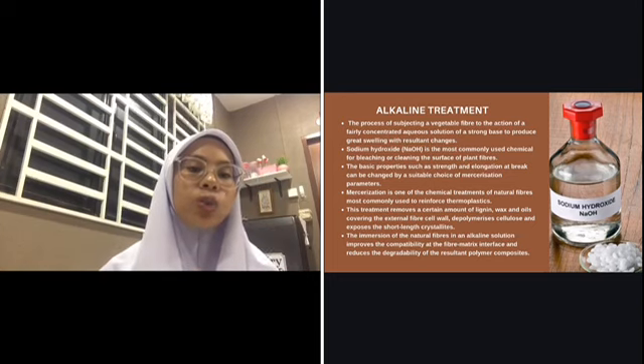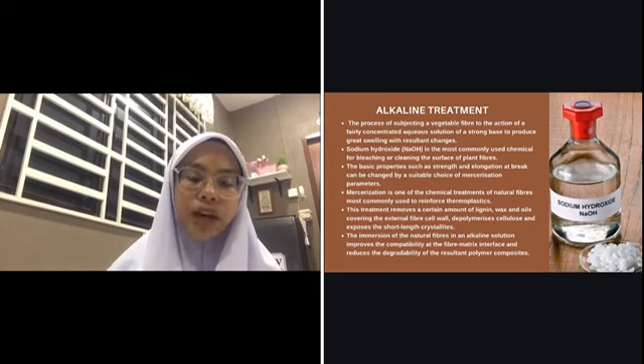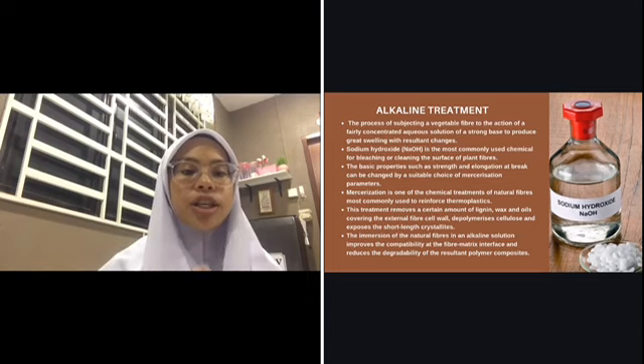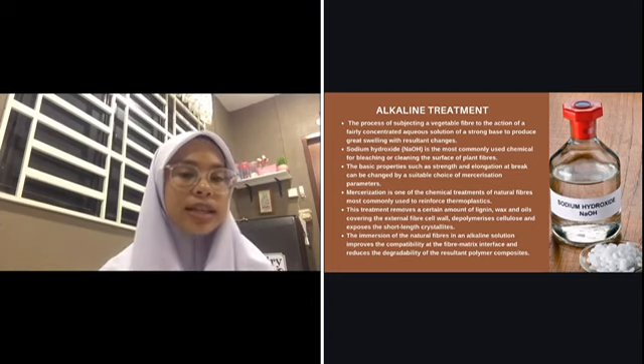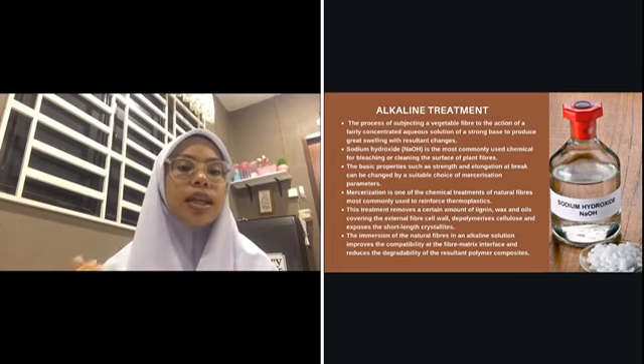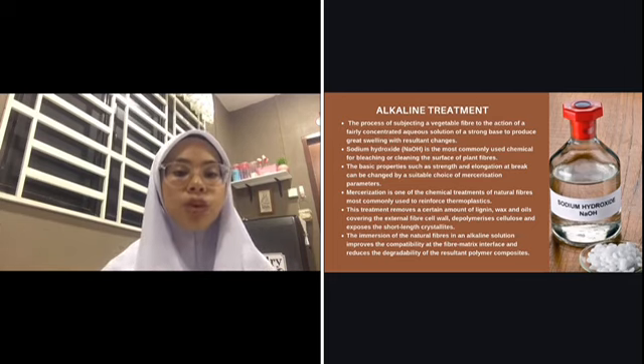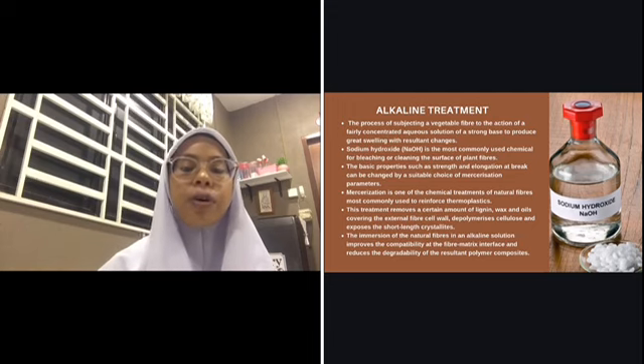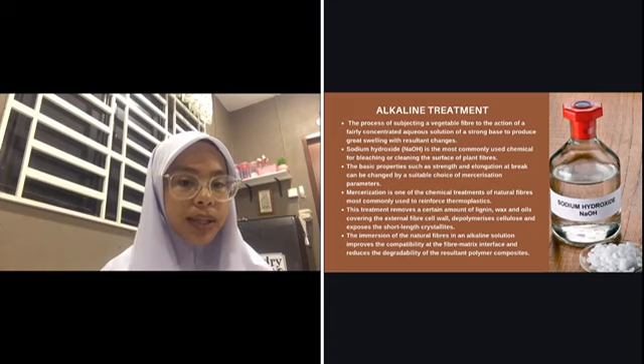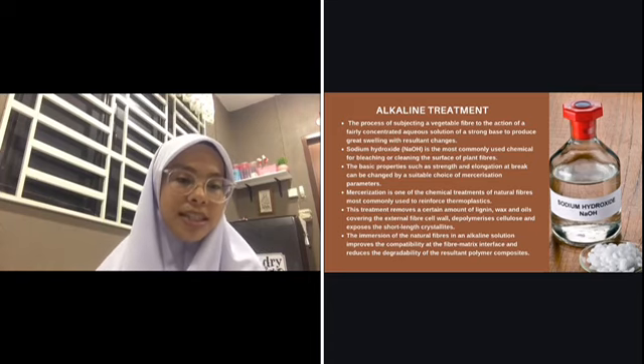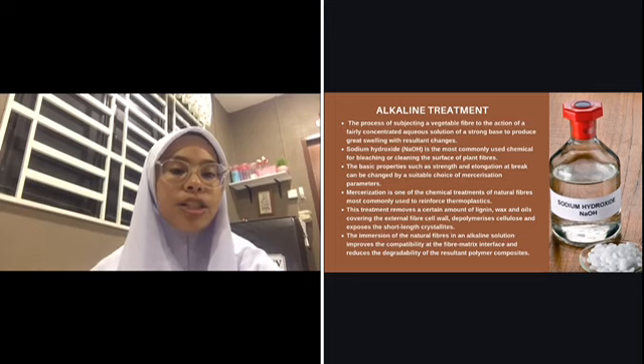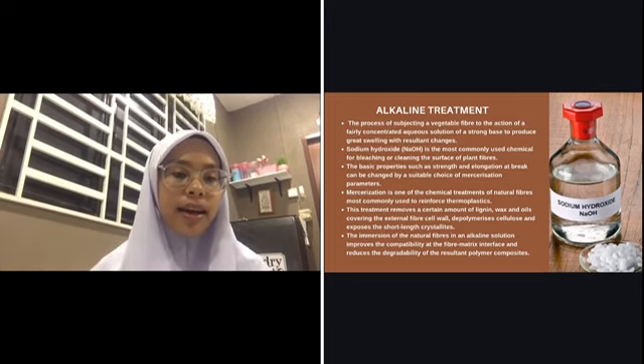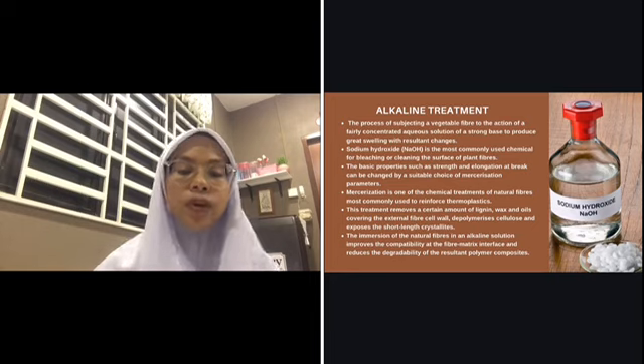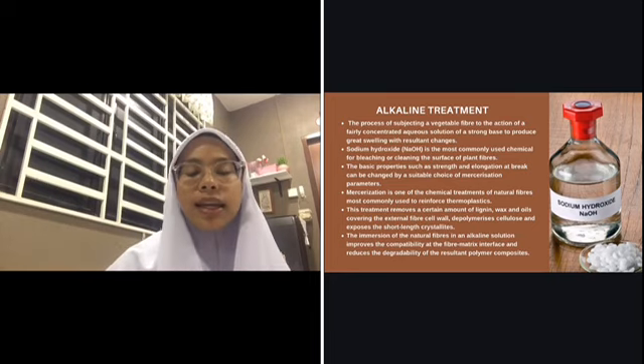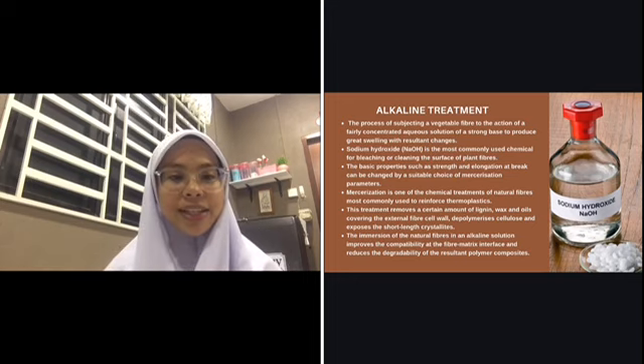So therefore, in order to improve the compatibility between the natural fiber and the polymer matrix, the natural fiber is immersed in an alkaline solution such as sodium hydroxide for a specific time duration at a specific temperature. It has been noted that the immersion of the natural fibers in an alkaline solution improves the compatibility at the fiber matrix interface and reduces the degradability of the resultant polymer composites. So to sum up, a lot of research has been done in the last decade, and it is proven that FRPC with the usage of treated EFB and polypropylene as the matrix can be used in various industries.